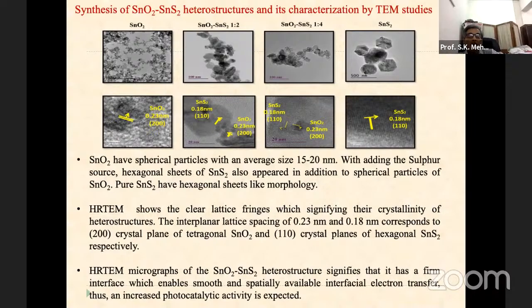Hexagonal sheets of tin sulfide also appeared, in addition to spherical particles of tin oxide, because tin sulfide has a hexagonal sheet-like morphology. So when you have the heterostructure together, you can see both in the particles. So HRTEM was taken, and it shows some data. Lattice spacing was 0.23 nanometer and 0.18 nanometer.